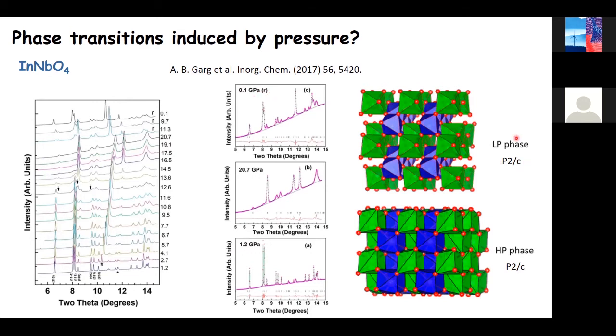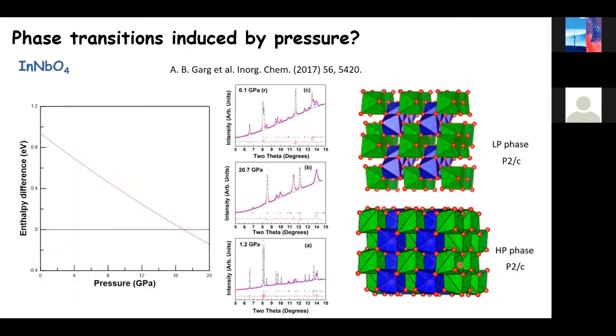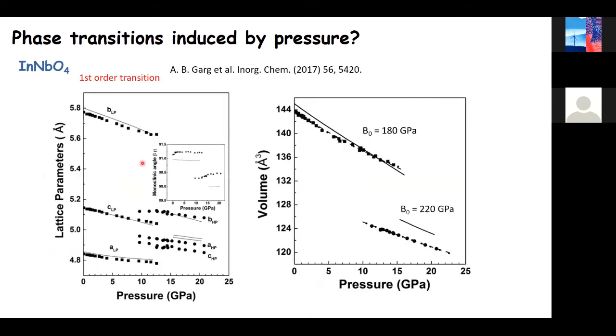Again, the low pressure phase of indium niobate is isostructural to the low pressure phase of indium tantalate, and the high pressure phases are also isostructural, with the two cations coordinated by 8 oxygens. Calculations also predict the same phase transition. You see here the enthalpy is crossing around 7 GPa. And again, we have a highly anisotropic behavior.